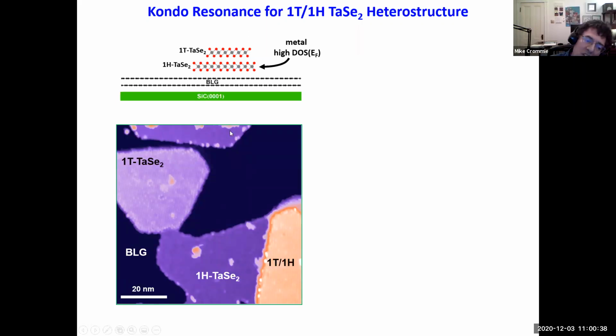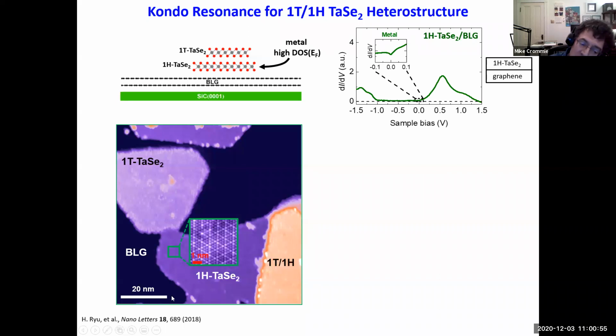In this STM image, you can see a patch of single layer 1T TaSe2, a patch of single layer 1H TaSe2, and then here you can see a patch where I have 1T TaSe2 on top of the 1H TaSe2. Now, when you zoom in on the 1H TaSe2, what you see is this very familiar 3x3 charge density wave, which is known to live on 1H TaSe2. And if you do STM spectroscopy, then you see a nice metallic density of states. There's a little dip, but it's a nice metal.